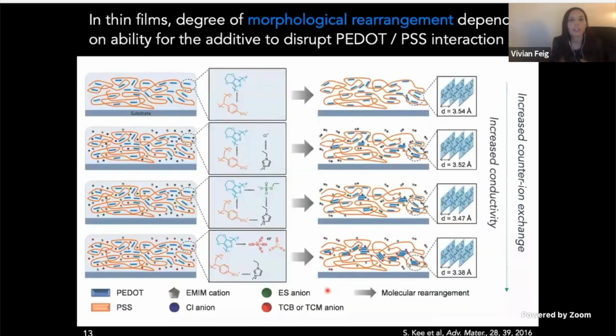And to understand really why this phenomenon occurs, there was a really nice recent study from Kwang-hee Lee's group at the Gwangju Institute of Science and Technology in Korea, which showed that basically it has to do with PEDOT and PSS being a two-component system. And so different additives can disrupt that interaction to varying degrees via counter-ion exchange. And so the more effectively that an ionic additive can do counter-ion exchange with PEDOT and PSS, the more effectively you can liberate PEDOT to phase separate into these more ordered structures that conduct electrical charges over more extended length scales, thereby enhancing conductivity.